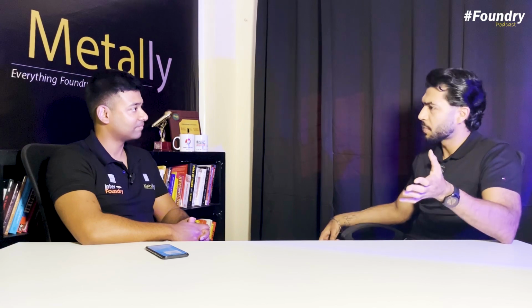And he has written a paper on SSF, which is solution strengthened ferritic ductile iron. Solution strengthened ferritic ductile iron. Okay, yes, I got to write this down. SSF, ductile iron. So basically what you do over there is you increase your silicon percentages up to 3.7, 3.8%. You reduce your carbon, you maintain your CE so that you do not go into a hypereutectic composition. Okay. So what's the result? You get a fully ferritic grade of ductile iron, say 500 megapascals of strength with 14% of elongation.